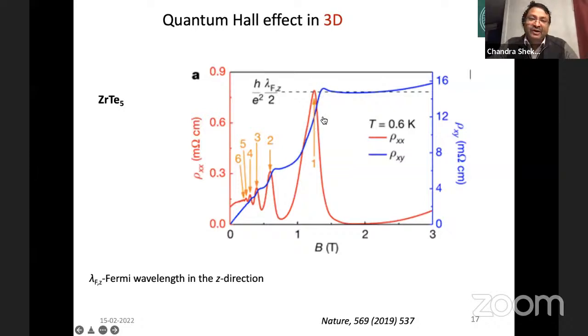You can also see a similar step-like behavior. But when you calculate the value of this step, it is not the same as the step of the two-dimensional system. This step can be quantized by the size of the Fermi pocket, because the material is three-dimensional, so we have to do some extra mathematics to quantize it. Here there is e squared by h, or h by e squared, but there is an extra term, a Fermi vector, Fermi wavelength.